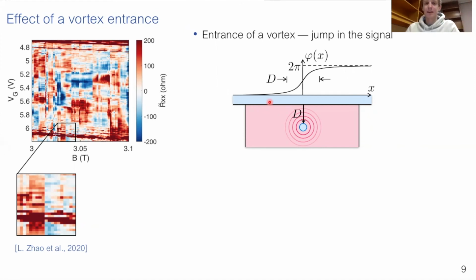Basically, when a vortex enters, it changes the landscape of the superconducting order parameter. There appears a kink in the phase at the interface, and the width of the kink is determined by the distance by which the vortex has entered. The magnitude of the kink is 2 pi. The conductance is again determined by the interference of Andreev processes happening in different places. And it's quite clear that the change in the superconducting phase will affect different Andreev processes in different ways, according to how this phase is distributed. So this is why the entrance of a vortex changes the conductance, because it changes the phases of individual Andreev processes.